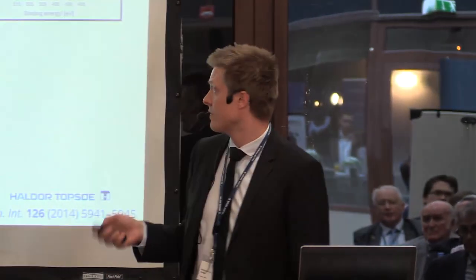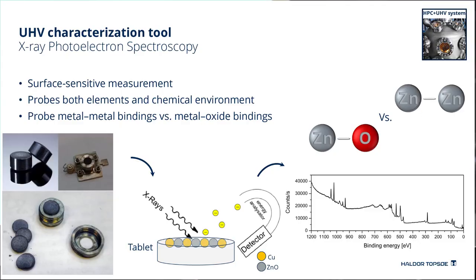So among the different characterizations which we had available is the X-ray photoelectron spectroscopy, or the XPS. We had temperature programmed desorption of hydrogen. And then we have the reactor frontal chromatography by nitrous oxide. In the ultra-high vacuum system, we had this X-ray photoelectron spectroscopy method available, and this is a very surface-sensitive method. So what we did was that we took the catalyst, we crushed it, and we re-pelletized it into some small disc-shaped pellets. These we could load in a special sample holder and mount it in the high-pressure cell and then transfer it into the ultra-high vacuum system.